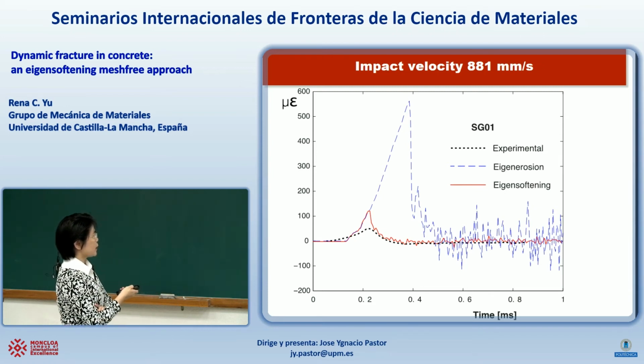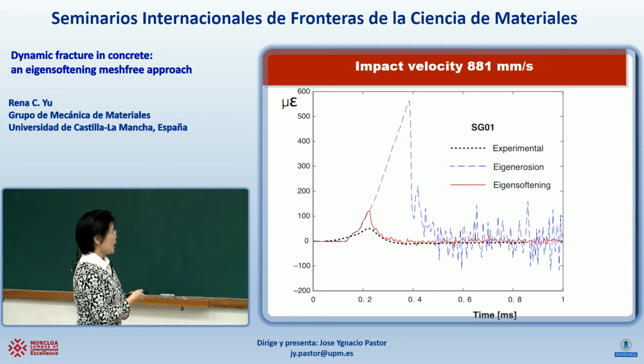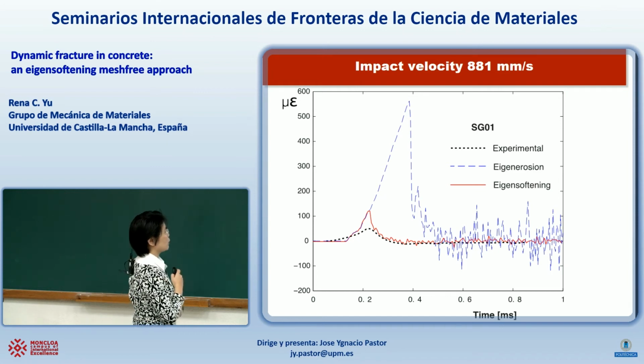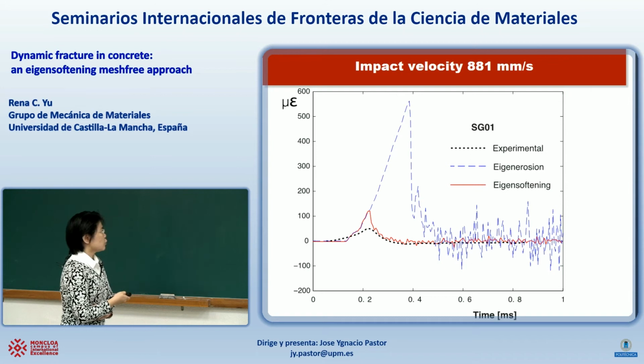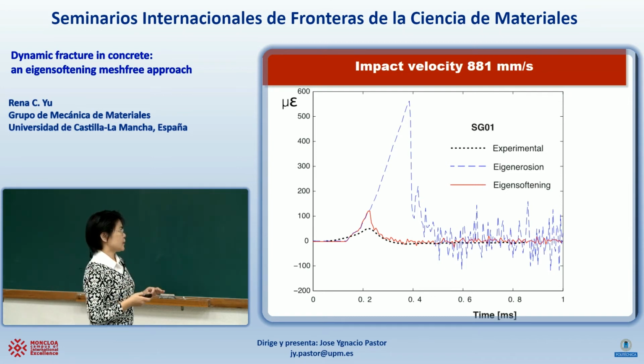This is a strain gauge. This is a microstrain with respect to time, and the black dots here are the experimental data. The red one is from what we developed for the eigensoftening approach, while this one is for the eigenerosion approach to fracture. So what we see here is that I have to say that the strain gauge measurement,